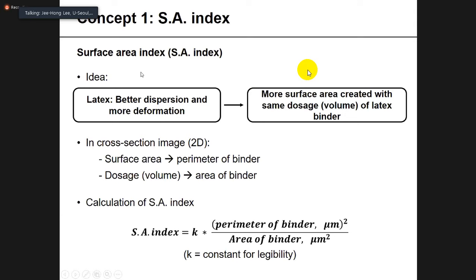It is derived from the idea that if latex shows better dispersion and more deformation within the coating layer, then more surface area would be created with the same dosage of latex binder. If you put this situation into a 2D cross-sectional image, the surface area would correspond to the perimeter of binder, and the dosage, which equals volume, would be the area of binder. So the calculation of the SA index would be the square of the perimeter of binder, divided by the area of binder. The constant K is just for legibility.